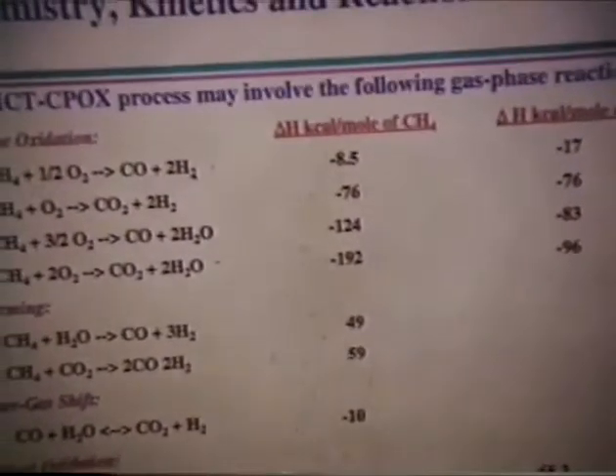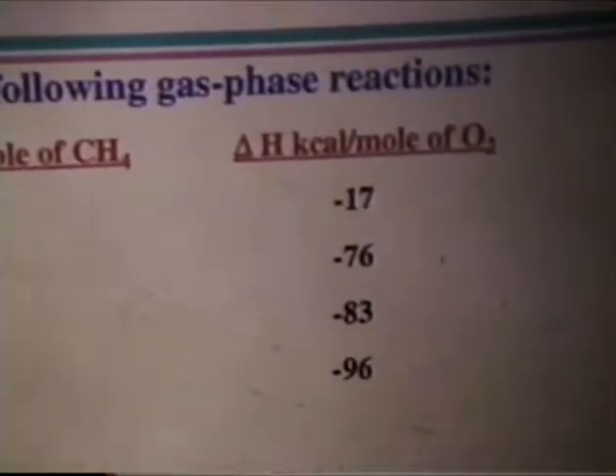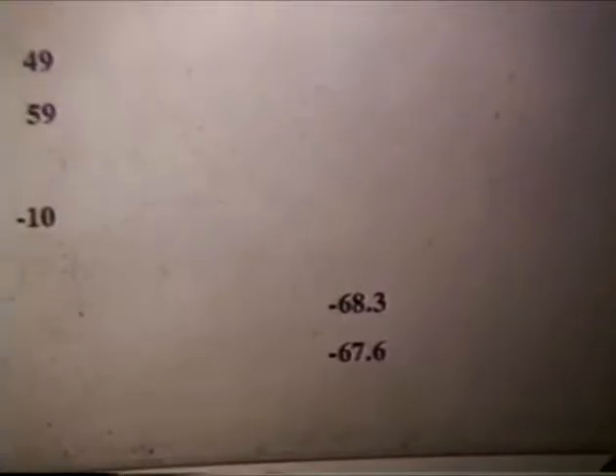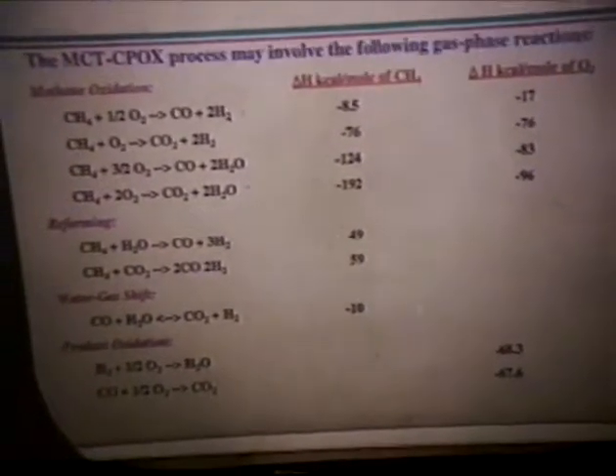The reaction network is pretty complex. First of all, you have your oxidation steps going on. Preferably, you want the first reaction to occur with CO and hydrogen. But what will happen is you will generate CO2 and also water. These reactions are more exothermic than the desired reaction. Then, once forming the water and the CO2 in situ, you can have reforming going on and water gas shift chemistry going on. Plus, you can have your product undergo oxidation during the process. So even though the problem looks simple, the kinetics and reaction network are complex.